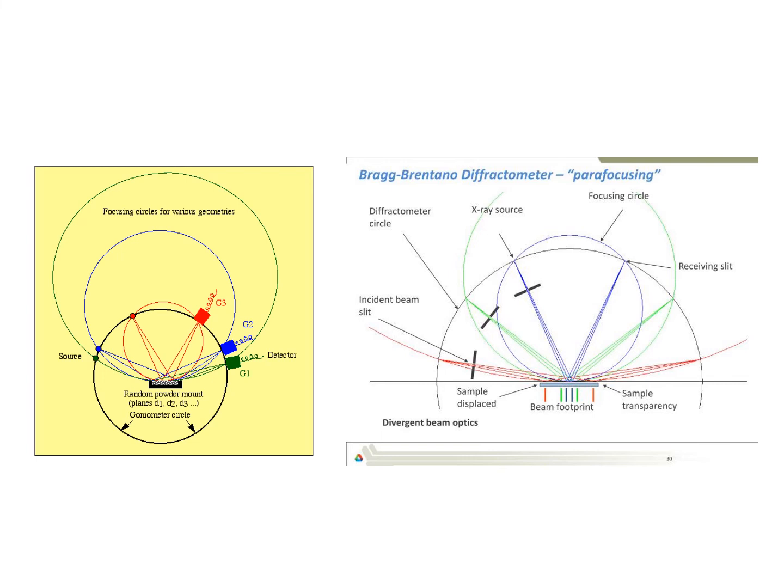But as I'll show you in a minute, these different ray paths are consistent with, in the case of a Bragg diffraction, so long as the angle of incidence of this point and the emission and detection is the same at the center of the specimen, these path lengths are such that two waves which are coherent here are also coherent here. That's just the nature of the geometry, which I'll describe in lecture 2.